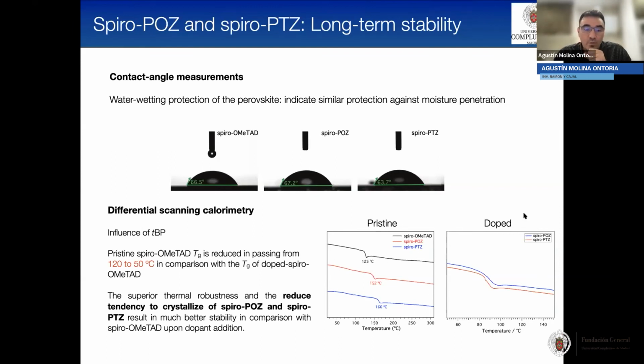What happened when we dope these materials with TBP, which is one of the dopants used in the device? In the case of Spiro-OMeTAD, this glass transition drops until 50 degrees. In the case of our molecules, it drops until 90 degrees, making our molecules superior, showing superior thermal robustness and therefore reduced tendency to crystallize in comparison with Spiro-OMeTAD.